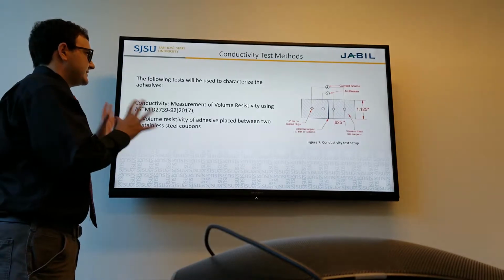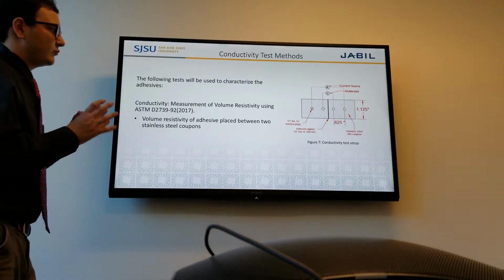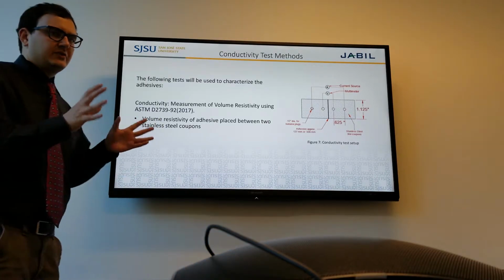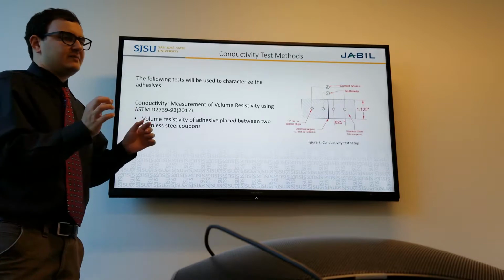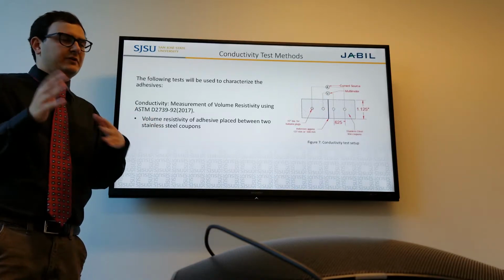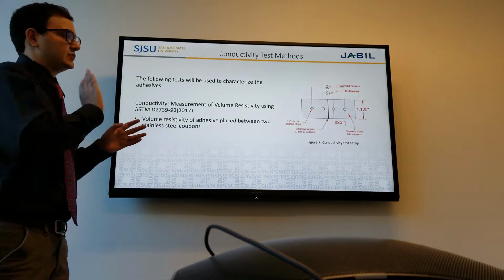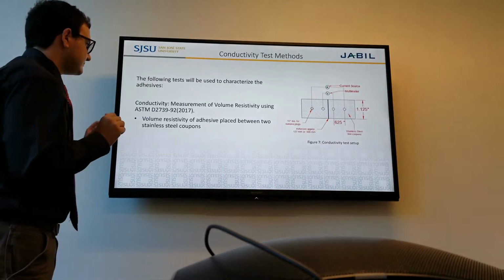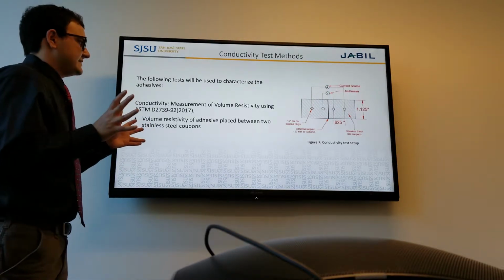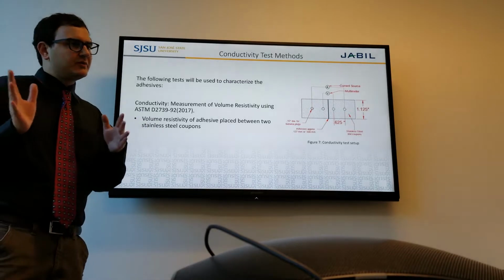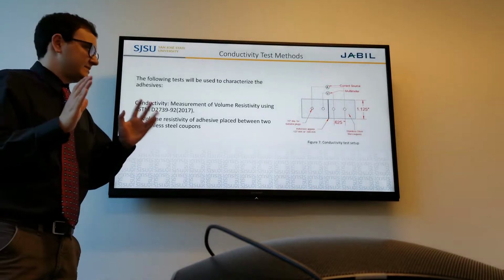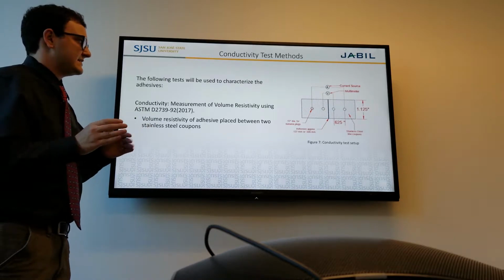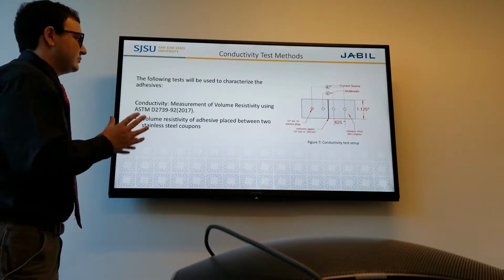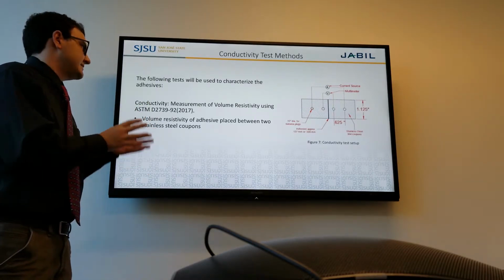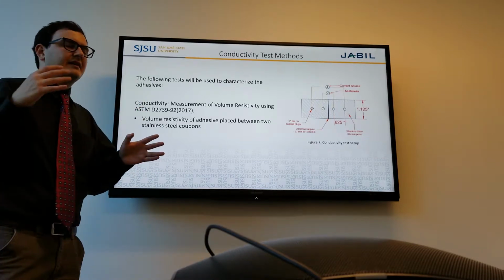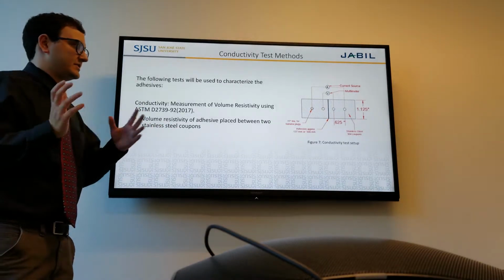So this is our conductivity test method. The way this method works is that you have 2 metal coupons and you have adhesive in between, and you measure the volume resistivity or the observed resistivity by taking the potential drop across this adhesive. So we use 2 stainless steel coupons. Stainless steel is affordable. It's metal. The resistivity is low, so it probably wouldn't interfere with our adhesive. And it was using a proven ASTM standard. We wanted to keep very close to the standard because developing and refining the standard would be a senior project unto itself.